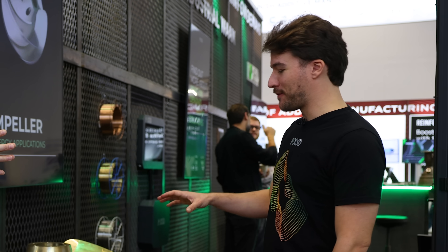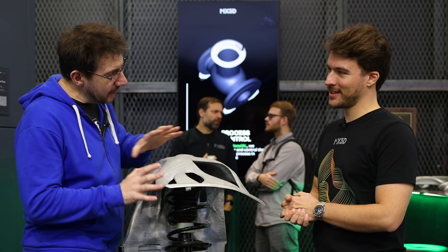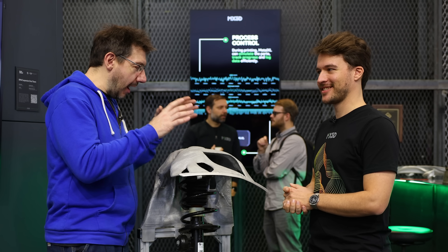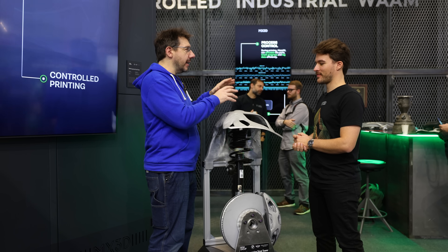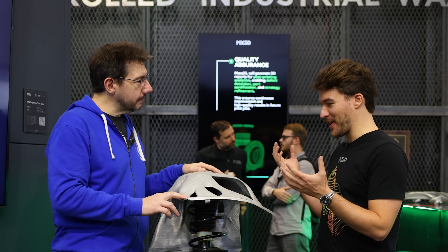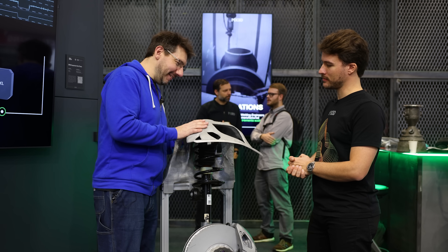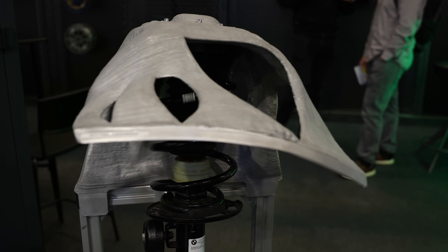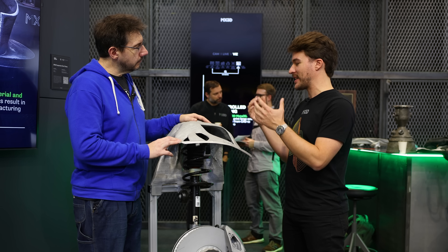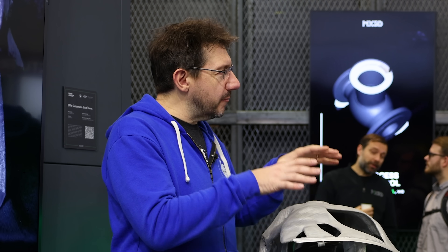Here's a seven-kilogram aluminum structural car part — one of the smallest parts at the booth. This is actually made by BMW Group and is fully 3D printed structural aluminum. It's only partially finished because BMW Group did structural load research and found that performance was acceptable, meaning they only need to post-process the surfaces that connect to other parts — drastically reducing cost while maintaining performance.